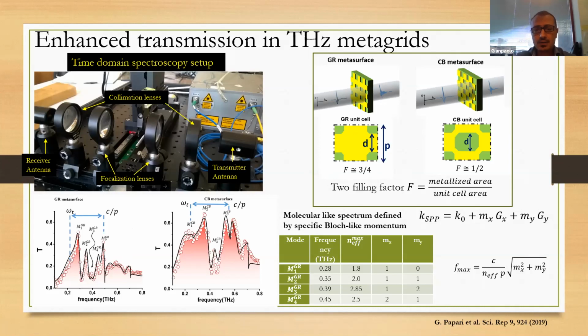What we are interested in now is that these metasurfaces have been investigated in this paper. And we have reconstructed all these modes, or if we like, excited states of the metagrids, which can be modeled through high-order surface plasmon polaritons, which are featured by specific momentum, and the frequency is much similar to the threshold frequency of a waveguide, but, of course, there is no relation with the geometry of a waveguide. There is a relation with the periodicity of the unit cell.